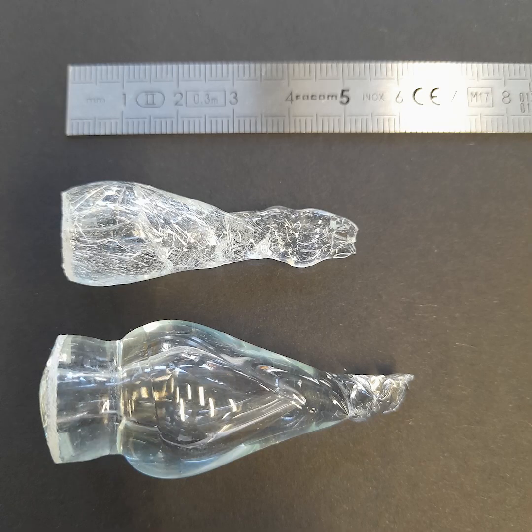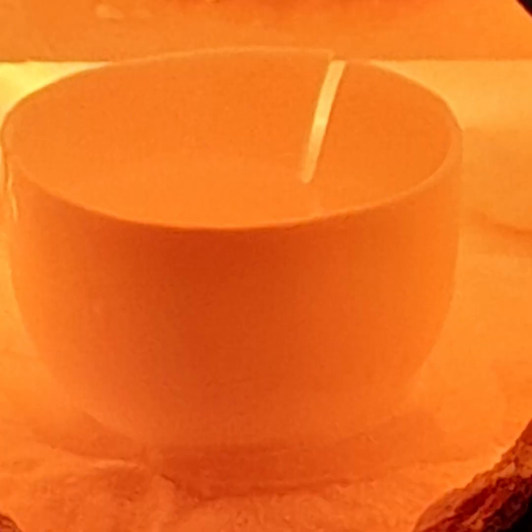Our first tests made me terrified, really, because if the crucible stayed intact, the glass wasn't compatible and shattered into a million pieces. It just wasn't stable. If the glass became more stable, the fluxes ate into the crucible and the crucible destroyed itself. So many of the small-scale tests I've been doing have failed. But my hunch has always been that I can make this work on a larger scale, and I think we have. So I'm going to open the kiln now, and I'm hoping everything's going to be intact.